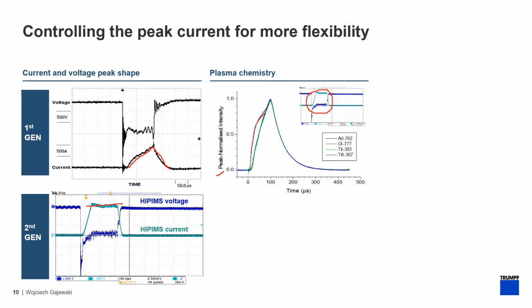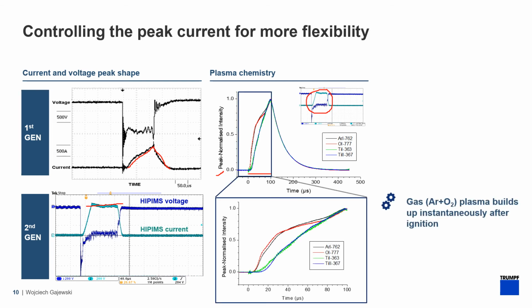The pulse is 100 microseconds long, and if we zoom in on this part of the pulse, we see that through all the pulse the intensity of both argon and oxygen is increasing, as we see here. But what is even more important, the intensity of the titanium ions is also increasing through all the pulse.